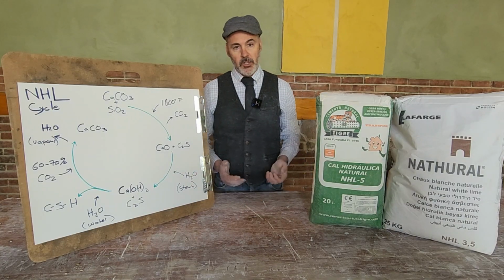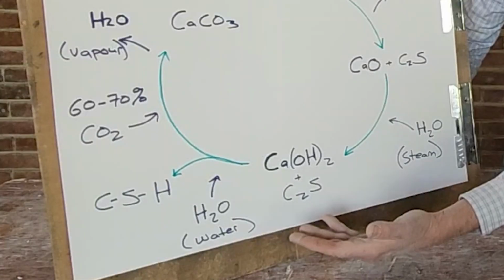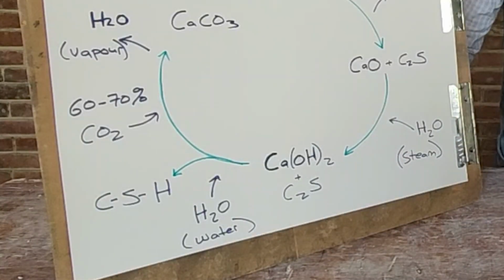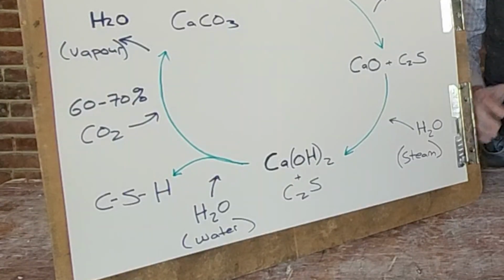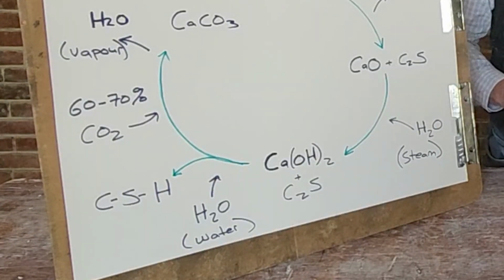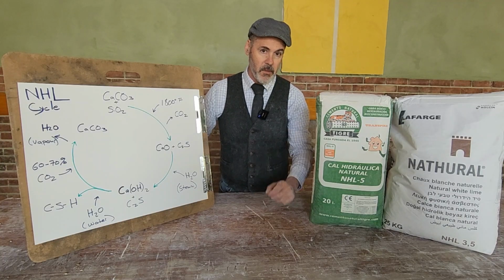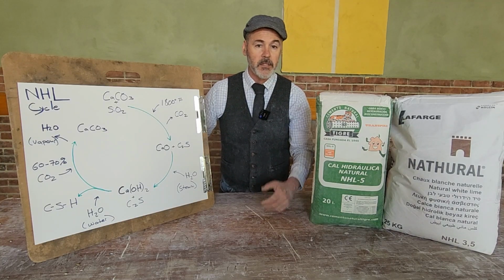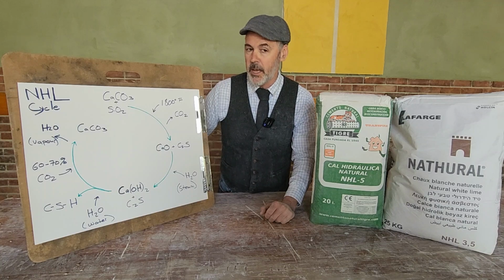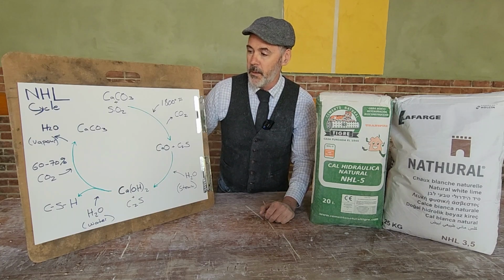When that arrives on the job site, the craftsman, mason or plasterer, will add liquid water to make his materials. And the first thing that happens is there's a chemical reaction that begins to take place with those belites forming hydrous calcium silicates, these crystals that set just with water. And that's where the natural hydraulic lime gets the hydraulic component of its name, the setting with water.